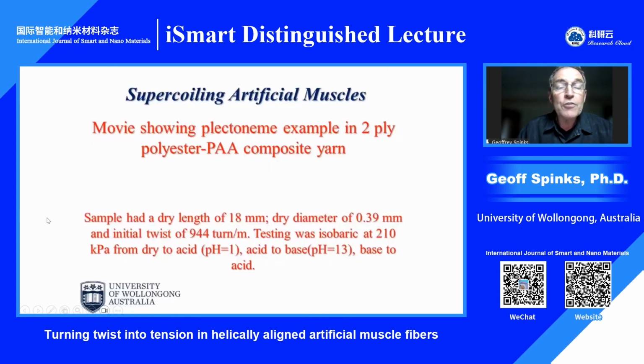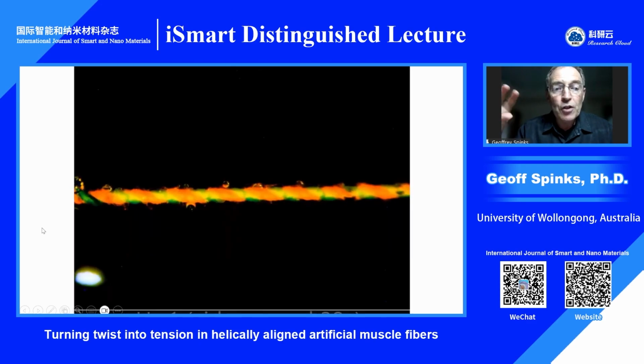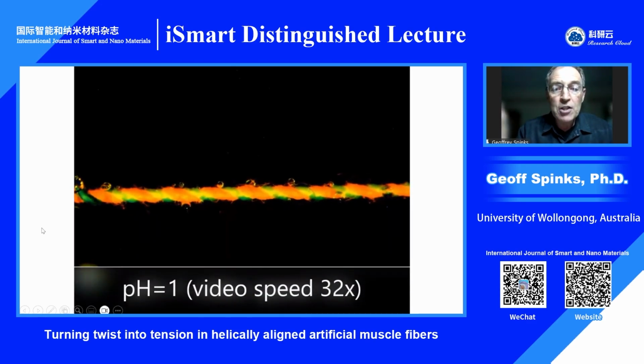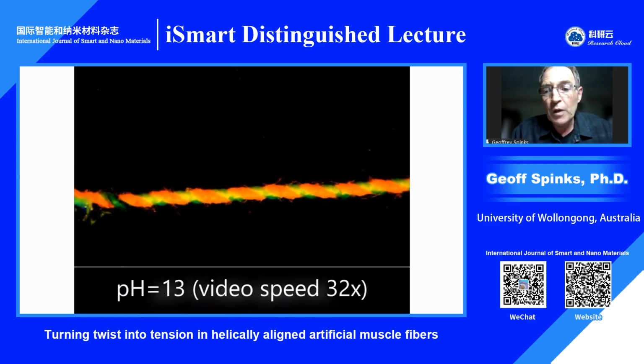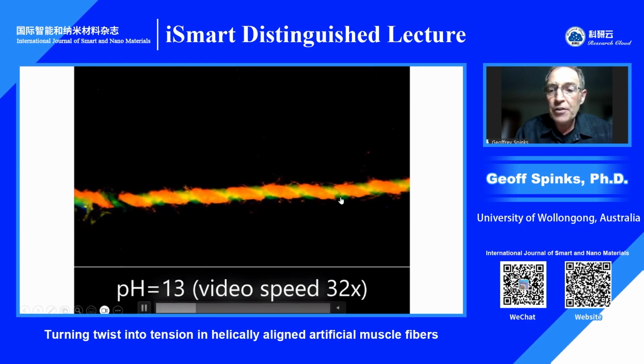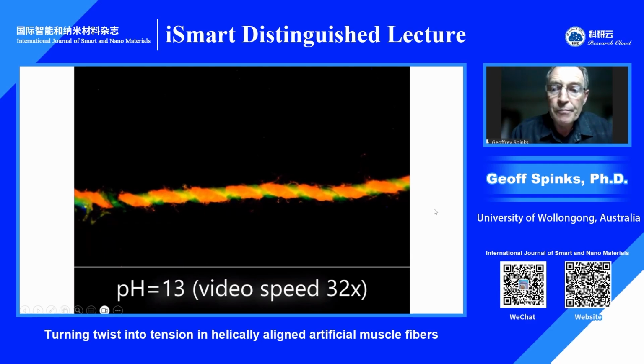Next, we wanted to figure out how much mechanical work was being performed by these materials. So we took the same samples. This time they're clamped at both ends in a way that stops rotation and applies a tension, but allows the ends to approach one another. So swelling in acid doesn't do very much at all. Further swelling in base, you'll see in a moment that a kink starts to form, which then quickly develops into a supercoil. So here we go.